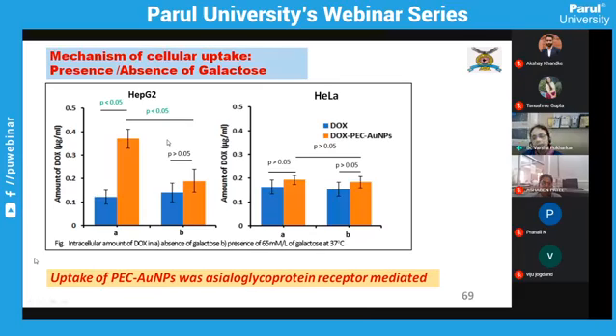Further, to explore the mechanism of uptake, we did the studies in the presence and absence of galactose. So here in the HEPG2 cell line, in graph A, the blue bar stands for plain DOX and the orange bar stands for the DOX loaded onto the pectin reduced gold nanoparticles. This is in the absence of galactose and here it is in the presence of galactose, which made a change in case of the HEPG2 cell line, which is asialoglycoprotein positive. But in case of HeLa cell lines, which are asialoglycoprotein negative, the presence or absence of galactose did not result in any change in the amount of DOX taken up by the cells. So this clearly indicated that the uptake of pectin gold nanoparticles was asialoglycoprotein receptor mediated.